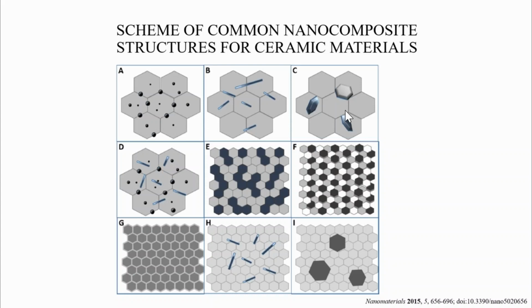A recent development in composite structure, as described in literature, introduced a combination of rounded and elongated nanostructured second-phase materials embedded in a traditional ceramic matrix, as depicted in picture D. The rounded grains of the second phase act to hinder matrix grain growth during sintering, creating a pinning effect aimed at enhancing composite hardness and strength. Meanwhile, the elongated grains, chosen for their toughening capabilities as previously discussed, contribute to the crack deflection mechanism.